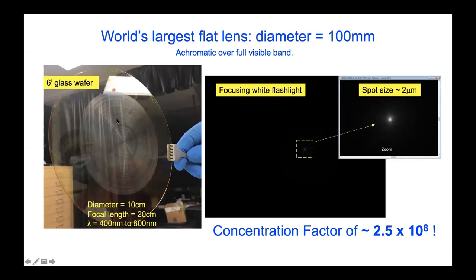Of course, one can also imagine using segments and aligning them, which is what's done in the case of space telescopes, which are, of course, much larger in terms of aperture. So that's really something we are working towards. But it's a good demonstration of what we think is possible in a single go. This focal length is 20 centimeters, so it's an f2 lens, again, fully achromatic from visible, and a little bit into the near infrared, 400 to 800 nanometers.